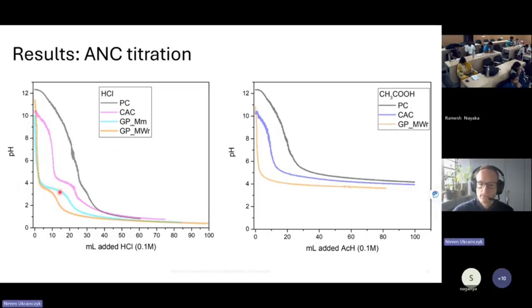And here is the pure. When you use pure clay, you have more geopolymer, so you have higher buffering effect. And when you use less pure with more quartz, like a filler, of course, you have less geopolymer and you have less buffering, but you have a better, more dense structure. This is why this material still performs better than this one. And the same thing for the acetic acid, but this one shows you the complete picture as a function of pH.